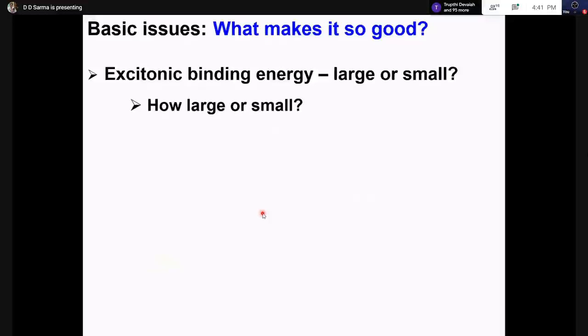The other question, which is fundamental, is the excitonic binding energy. I am talking about the electron and hole that get generated when a photon is absorbed. But this electron and hole get generated locally at the same site. And then they feel their attraction, Coulomb attraction, because one is positively charged, the other is negatively charged. And there's an associated binding energy, and that binding energy is called the excitonic binding energy. If the excitonic binding energy is very large, then the electron and hole will not like to get separated and will have very poor photovoltaic property. But if it is small, they'll get separated very easily. So it's a very important parameter to quantify the efficacy of